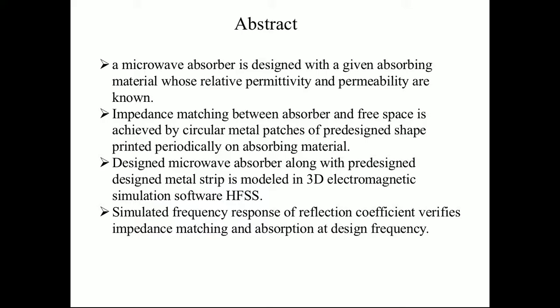In Abstract, a microwave absorber is designed with a given absorbing material whose relative permittivity, or epsilon r, and permeability are known. Impedance matching between an absorber and free space is achieved by circular metal patches of pre-designed shape printed periodically on an absorbing material. Designed microwave absorber along with pre-designed metal strip is modeled in a 3D electromagnetic simulation software, HFSS. Simulated frequency response of a reflection coefficient verifies impedance matching and absorption at a design frequency.